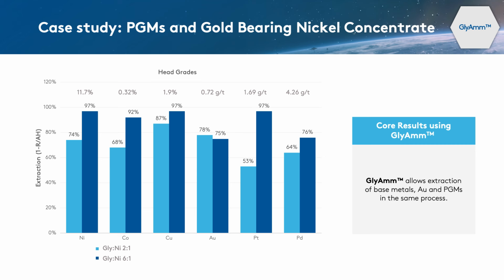As you can see, there were 74% of nickel extracted, and similar for cobalt. And for copper, it managed to extract 87%. And at the same time, 78% of gold was extracted, and 53% of platinum, and 64% of palladium extracted. If we further increase the glycine dosage to a molar ratio of 6:1 nickel, the extractions can be further